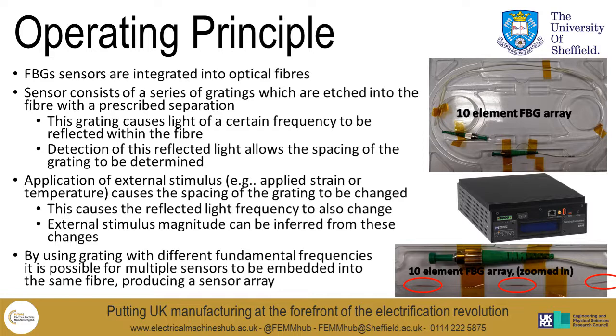By detecting this change in frequency, it's possible to infer the magnitude of the stimulus which was applied to the FBG. Because FBGs only interact with light in a certain frequency band, it's possible to put a number of them in an array on the same fibre, as long as they're all set to work at different grating spacings and therefore different light frequencies. Doing so allows you to have one single fibre with multiple sensors, which can potentially simplify the cabling process when producing the machine.